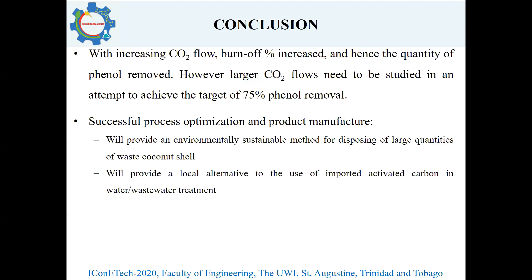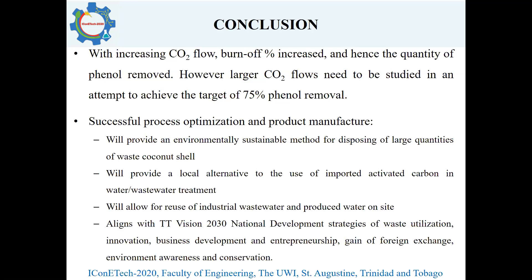In conclusion, I found that with increasing carbon dioxide flow, the burn-off percentage increased and hence the quantity of phenol removed. However, larger carbon dioxide flows need to be studied in an attempt to achieve the target of 75% phenol removal. Once the process is optimized successfully and an effective product is made, this would provide an environmentally sustainable method for disposing of large quantities of waste coconut shell — a local alternative to imported activated carbon in water and wastewater treatment — and will allow for reuse of produced water on site. This aligns well with the TT Vision 2030 national development strategies in the area of waste management and sustainability.